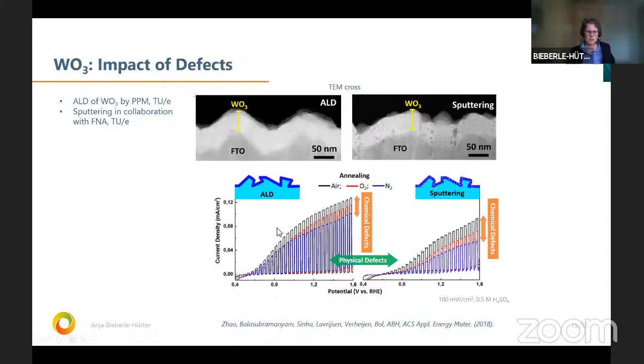So let me show you here the difference. So on the left is the ALD, on the right is the sputtering. We relate the different performance, overall performance, which is higher for the ALD than the sputtering, to these physical defects. But what we also find is that there is an effect of, we call it here, chemical defects.